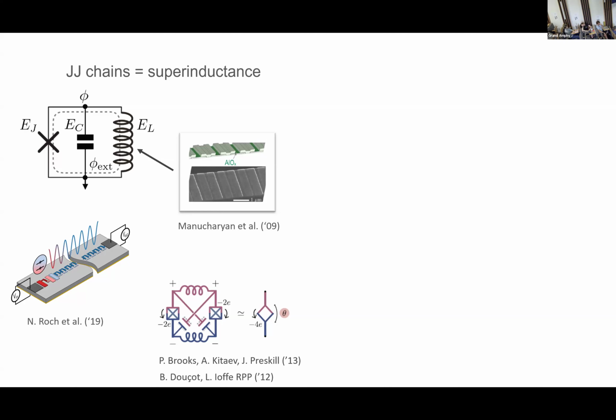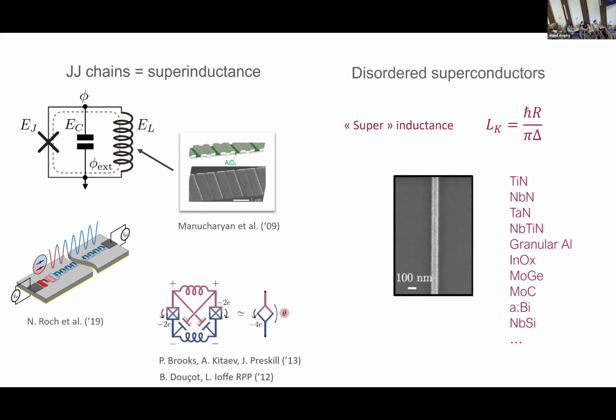The deal is that to attain very large inductance, so we are talking about microhenry total, this chain is a little bit complicated. It's doable, the technology exists, people can do that in the lab, but imagine you need to make a 1 million qubit quantum processor, each of them with a chain of, I don't know how many junctions, 1,000 perhaps, or a few hundred. Then scalability and errors in the fabrication become drastic, right? So it's super tempting, obviously, to replace the chain by just a line: take your preferred disordered superconductor, you lift off, you etch, whatever, and there you have 1 nanohenry per square, you make a couple of hundred microns, and you get your inductance.